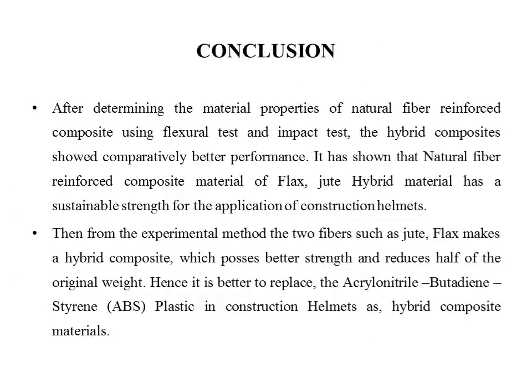Conclusion: After determining the material properties of natural fiber reinforced composite using flexural test and impact test, hybrid composites show comparatively better performance. It has been shown that the natural fiber reinforced composite materials of flax and jute hybrid material have sustainable strength for the application of construction helmets. Then, from the experimental method, the two fibers, jute and flax, make a hybrid composite which possesses better strength and reduces the weight to half of the original weight. Hence, it is better to replace the acrylonitrile butadiene styrene plastic construction helmets with a hybrid composite material.